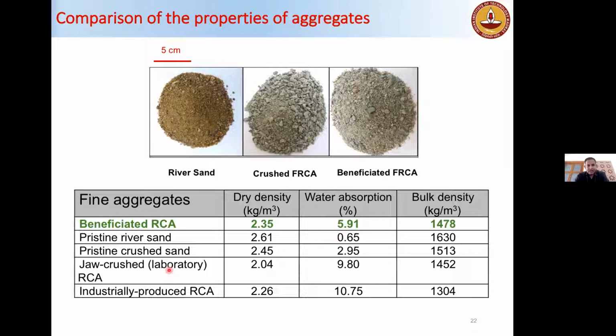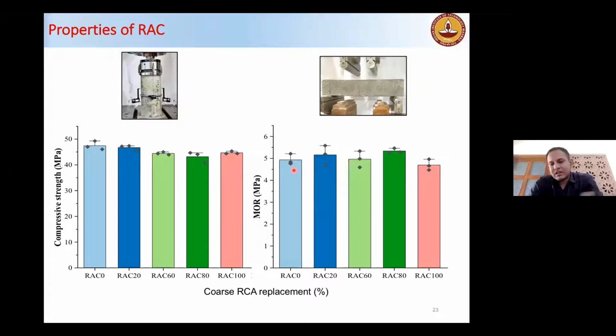Let me just give you a glimpse. We have replaced granite aggregate with coarse recycled aggregate at 0%, 20%, all the way up to 100%. So the bottom line is that with the treatment process, you can optimize the use, and you can use up to 100% of the recycled aggregate after the treatment.